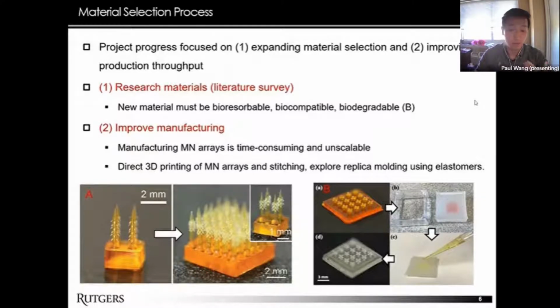The other way is through replica molding using elastomers. Here we cast a mold of our needles in a curable elastomer to create a mold, which we fill with our selected material and then cure again. You can see the process in the bottom right figure. Afterwards, we pop out the completed microneedle array. This method is a lot trickier, but it has the best potential for fast manufacturing. Our original microneedle model needs to be easily removable from the elastomer molds, and this is a major challenge.